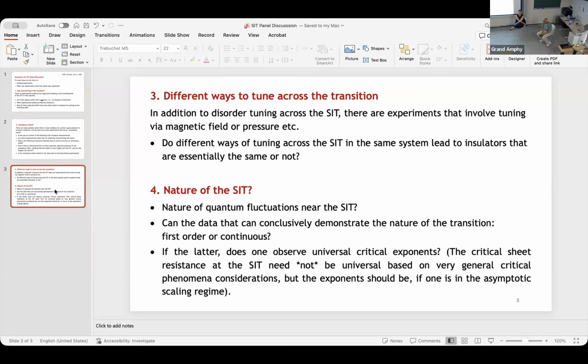Yeah, actually surface and interface scattering is stronger and stronger in thin films. I think that's the reason. But then it is a different kind of disorder than the one the strongly disordered community usually talks about, because the latter is about either impurities or amorphous structure. So it's intrinsically a bulk property. It is now clear that you cannot substitute one for another. It's just two different knobs, two different effects that you can, to some extent, unite in certain physical situations, but not in all of them.